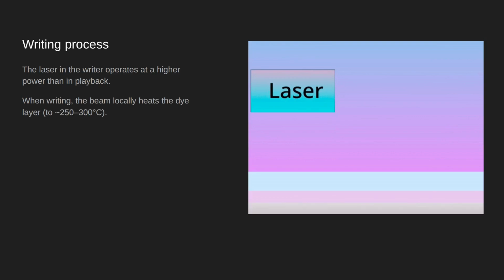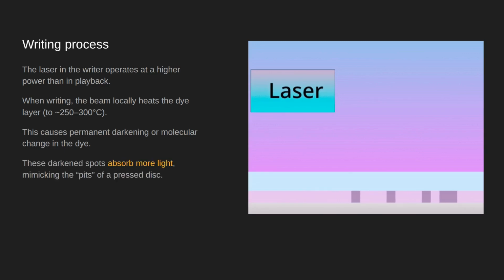Okay, so the laser functions at a higher power than is normally used during reading, much higher. And when it does fire the laser, usually it heats the dye in that area of the disk to a much higher temperature, between about 250 and 300 degrees Celsius. And as it does that, as you can see here, because where it's hit, it causes a permanent darkening or a slight molecular change in the dye. And because it's darker, those darker spots absorb more light, which effectively, when the CD is reading it, has the same effect as a pit on the pressed disk. Okay, so that's how singly writable DVDs or CDs work.